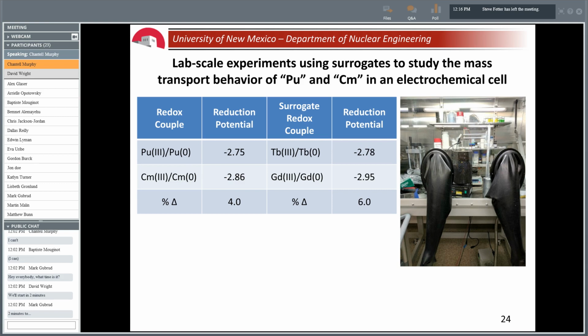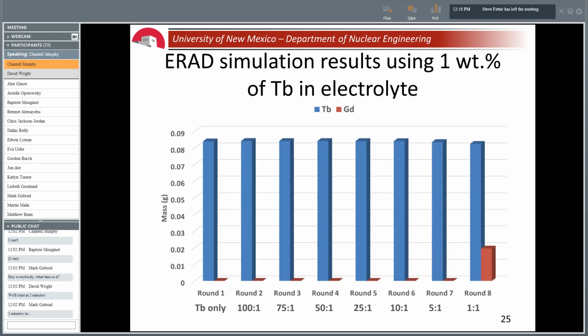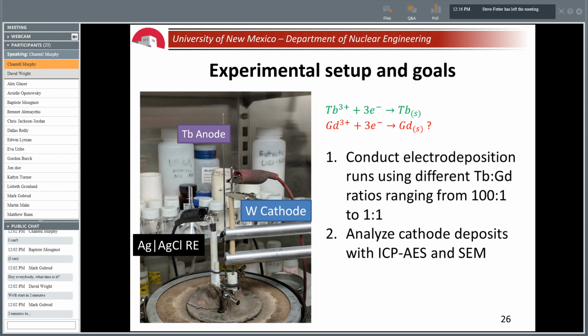I began by doing ERAD simulations of my experimental test plan. I did 8 rounds with a different ratio of terbium to gadolinium. These are the results from using 1 weight % of terbium in the electrolyte and then changes in gadolinium concentration for each round. Through all 8 rounds, 80 milligrams of terbium deposited on the cathode, and it wasn't until the ratio was about 1 to 1 that gadolinium started to co-deposit as well, at about 20 milligrams. So those are my ERAD simulations, and I want to see if my experiments will also result in similar results.